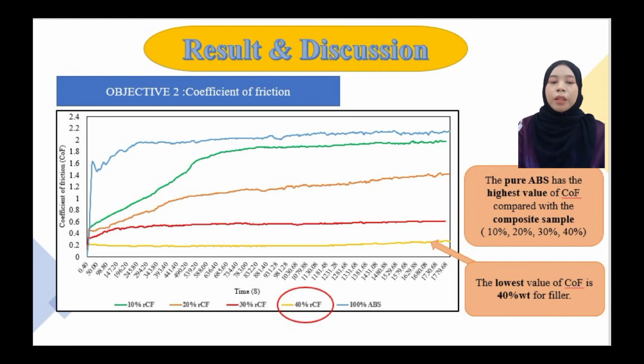The graph shows the coefficient of friction of the composite sample against the test time, which is 30 minutes or 1800 seconds, under a 15 Newton workload and 15 millimeter track radius for a rotary experiment using pin on disc. The pure ABS has the highest coefficient of friction, in the range of 2.10 to 2.15, compared with other composite samples. This might be due to the rough surface of the sample. The lowest value of coefficient of friction is at 40% recycled carbon powder filler loading.